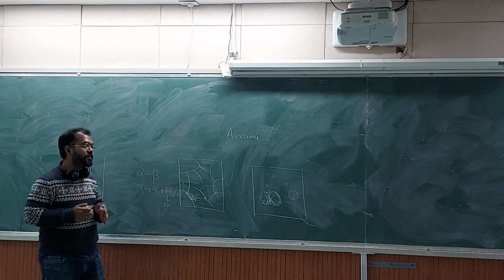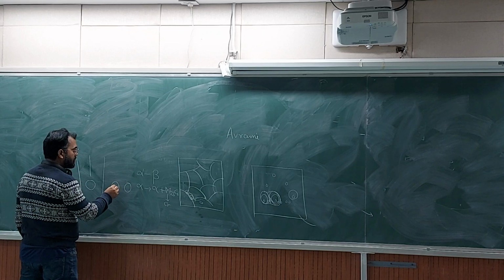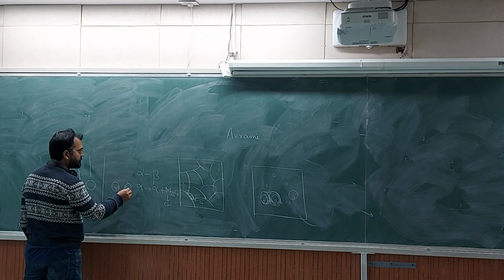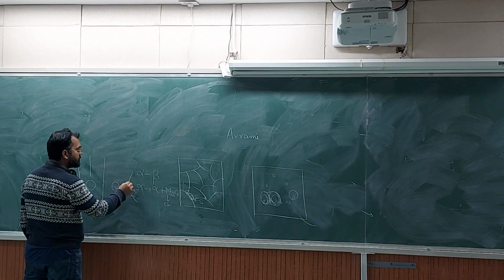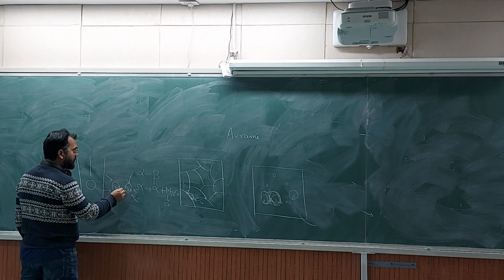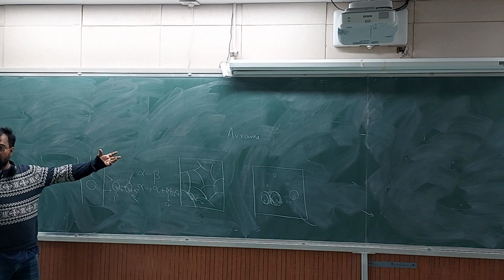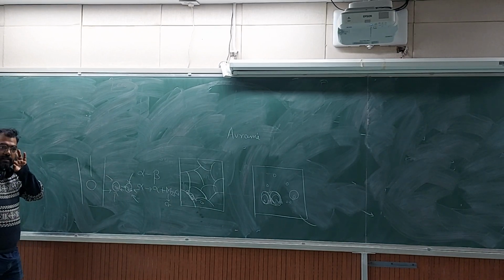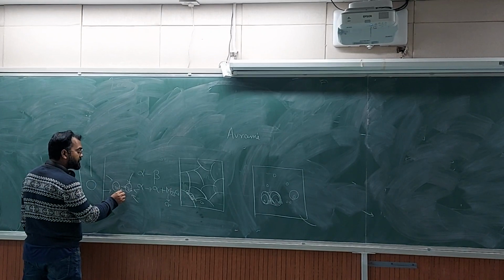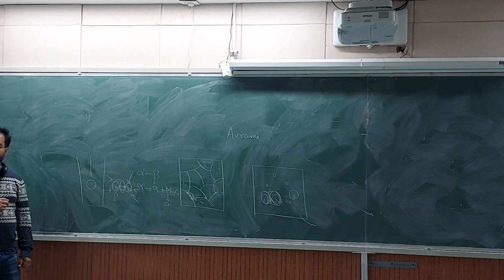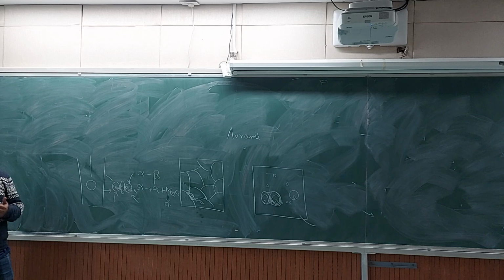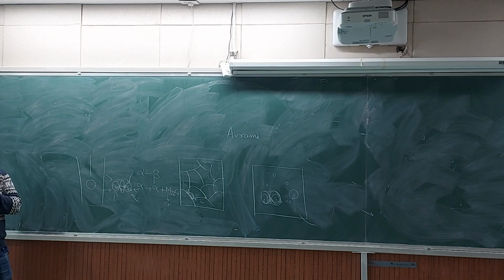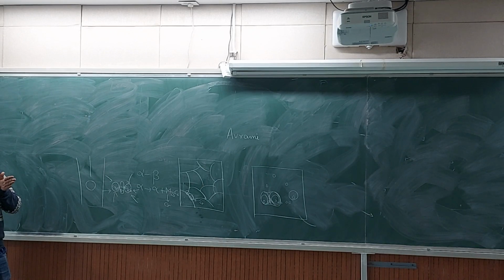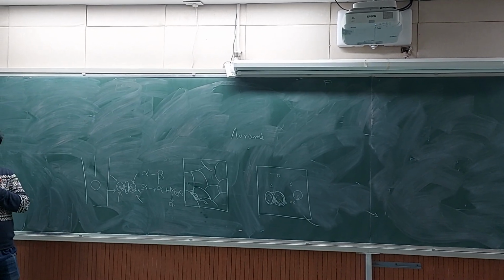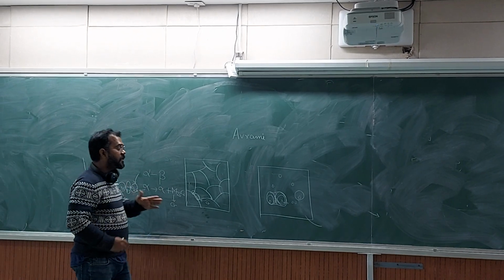because when they grow, suppose you have two adjacent precipitates of Cr23C6. The atoms which are needed for formation of these precipitates are coming from all directions. Chromium is traveling from all directions, carbon is diffusing from all directions, but the highest probability of diffusion, so depletion of the solute, is here. Whatever chromium or carbon is there, that has a possibility to go to either of the precipitates. So more depletion will be happening in between them, and then there will be a zone where so much depletion has happened that they cannot join anymore. There will be no growth, right? Which is not the case with voids.